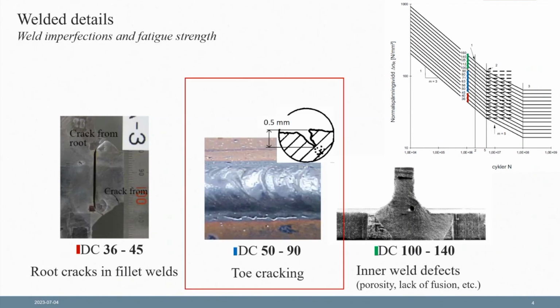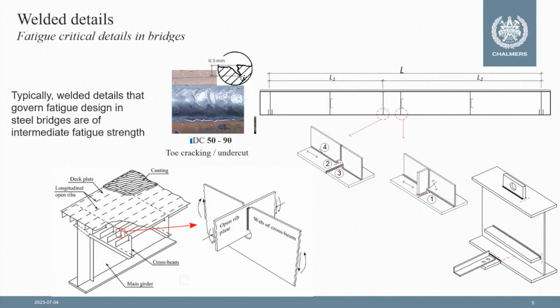Between these two categories, we have the category which is often determining the fatigue design of welded details, for example, in bridges. These are welded details that have intermediate fatigue strength, something between 50 and 90 detail categories. In this category of details, fatigue cracks start typically from the weld toe region. And we see these details in many types of bridges, orthotropic bridge decks, bridge girders with different types of details. In all these details, cracking starts from the weld end or from the weld toe and grows in the base metal. So they are typically determining the fatigue design. They put the limit for which stresses we can allow for a specific design lifespan.